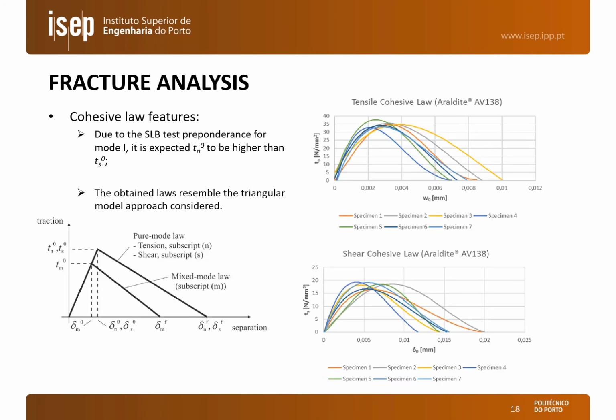After having the fracture envelopes, the next step was to obtain the tensile and shear cohesive laws of the adhesives by differentiation of the G1 and G2 as a function of the openings of the crack in tension and shear, and we have here the results obtained for the brittle AV138. We can see that we have some scatter between each curve of each adhesive, but we have a good agreement in the maximum stresses and also the fracture energy, which is the area under the cohesive laws.